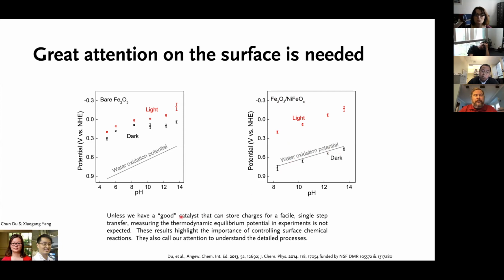So the point I wanted to make is that unless you have a good catalyst... what does a good catalyst in such a system mean? Well, it means that it can store all the charge for water oxidation. That's a four electron, four proton process. It can store all the charge and dump those electrons in a single step, or collect those electrons in the oxidation stage reaction in a single step. And then this process has to be reasonably fast. Otherwise, you're not really expected to measure the thermodynamic equilibrium potential. So this is a very important lesson for us to keep in mind.